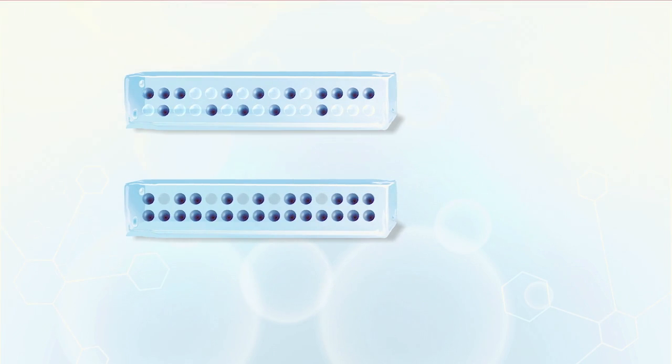For an N-type silicon material doped with Nd, assume that there will finally be P holes in the material. Then, we have the number of electrons N equal to P plus Nd because each hole also corresponds to one electron. At equilibrium, we have P times N equal to Ni squared. That means we have to solve for P from the equation P times (P plus Nd) equal to Ni squared.